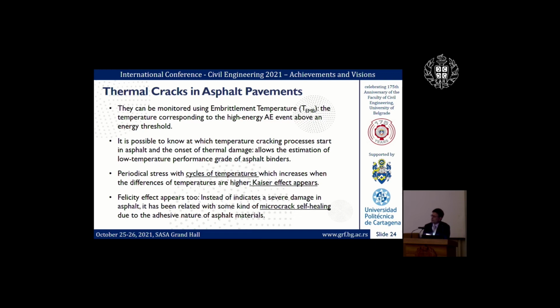Another application, this one in pavements, is to monitor the thermal cracks that can be produced there due to the thermal cycles, the high variation of temperature. To monitor this, the concept of embrittlement temperature has been developed, which is the temperature corresponding to a high energy event above an energy threshold.